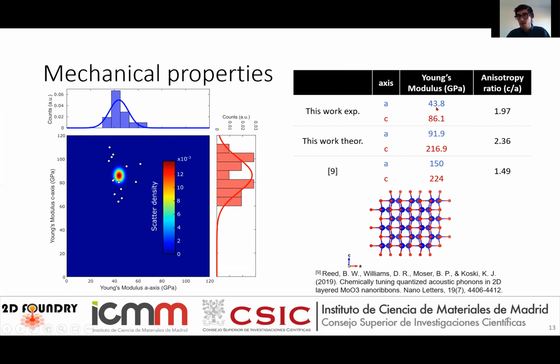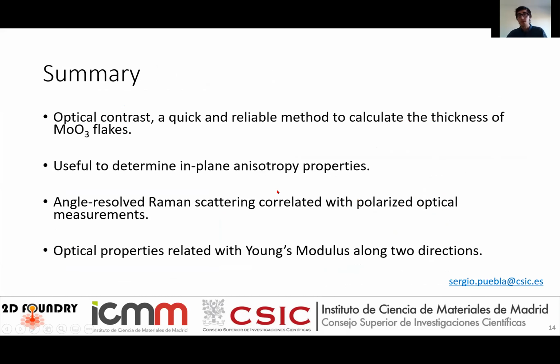For example, you see that this one differs a little bit, but the anisotropy ratio, which is the division of the Young's modulus of the c-axis over the a-axis, goes between these two values. So we find this method a good one. As a summary, we have found these methods to calculate the thickness of the molybdenum trioxide flakes. We think that it's a fast and reliable one.